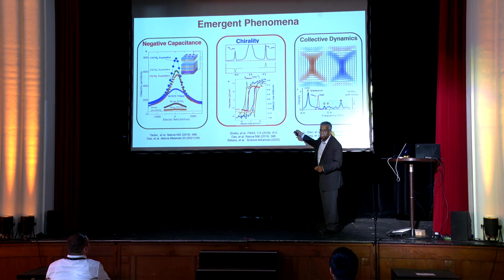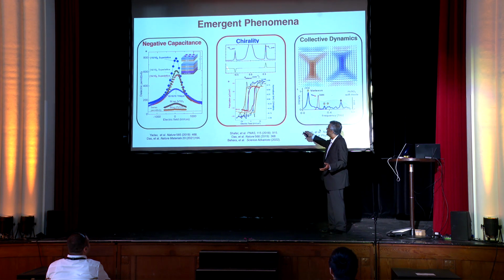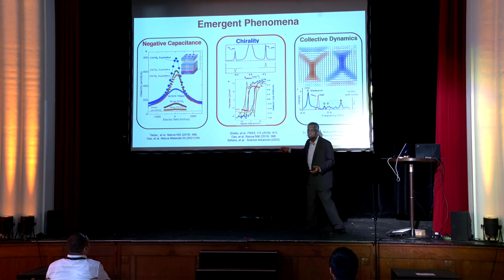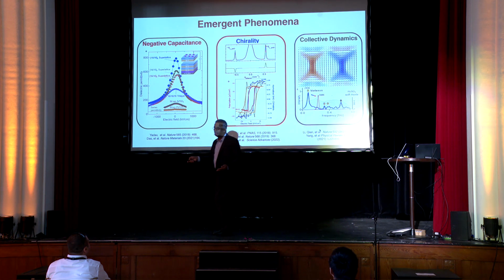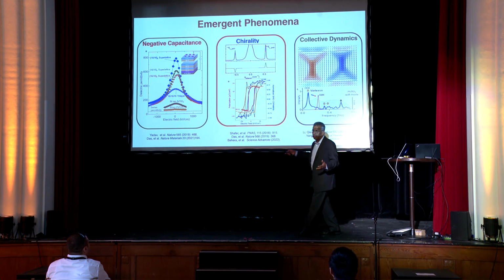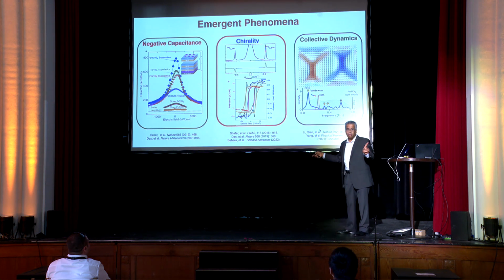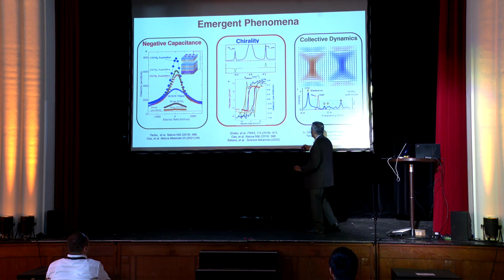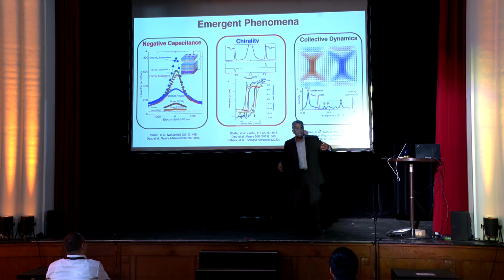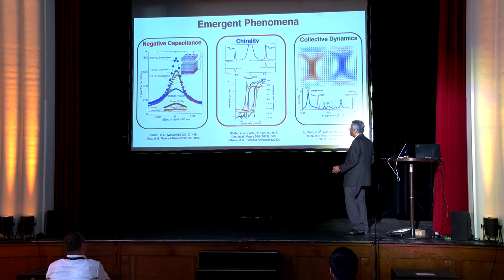This is resonant soft X-ray diffraction. The LBL people have been fantastic in doing this work. They helped us a lot. And you can start to see circular dichroism in those measurements. Typically, circular dichroism is because of natural optical activity, or if you have ferromagnetism. This material effectively behaves like a ferromagnet. It's not a ferromagnet. It behaves like a ferromagnet. And you can switch that chirality with an electric field back and forth. You can now start to do it with second harmonic measurements, near-field measurements, and so on.